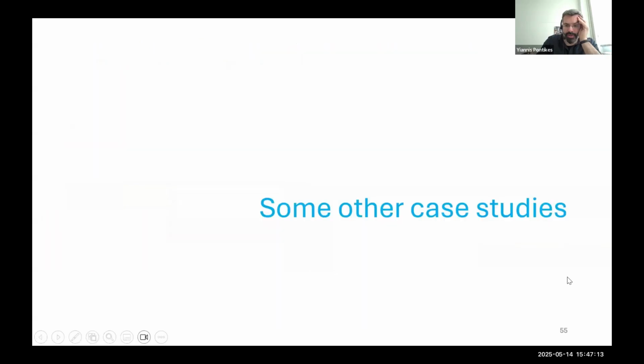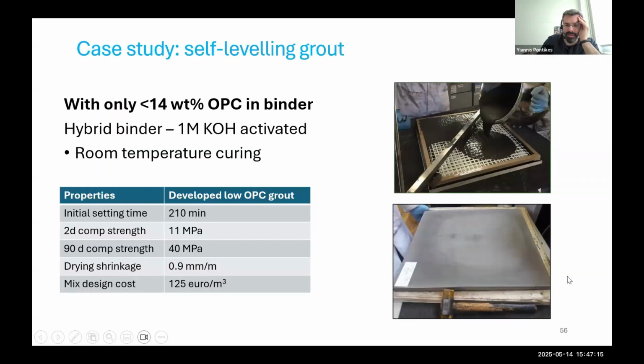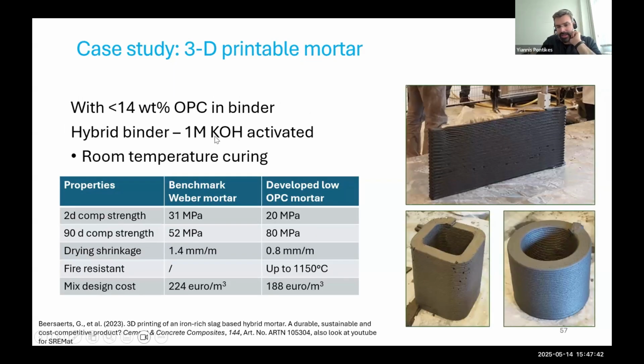All right. Now some other case studies. We've done self-leveling materials. For us, it's called grout. In this case, you have to see about also initial and final setting times and compressive strength, how it develops. So if you want to make tiles, you can even sell them as tiles, but you need to take into account, of course, your cost, your mix design. In this case, we use a hybrid binder, potassium, so it doesn't also have an efflorescence. And again, it was slag for the most part.